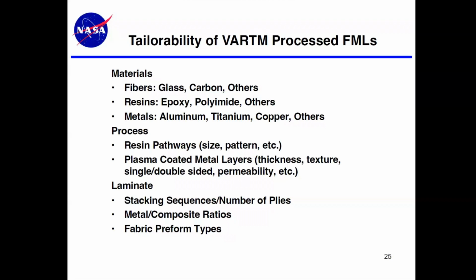The process itself also has some variables: the resin pathways that we put into the foil materials, the size and the pattern can be varied. The plasma coated metal layers, the thickness can be controlled. The texture, you can coat on either one side or both sides of a fabric. You can make the metal coating either more or less permeable depending on the process parameters. And then within the laminate itself, you can change stacking sequences and number of plies. You can vary the metal to composite ratios, and also obviously different preform types can be utilized. So there are a lot of variables that allow tailorability for desired applications with these types of materials.